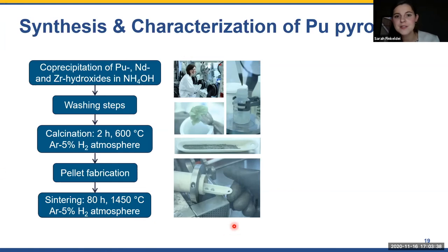And the challenges for the synthesis route were that whenever you work with plutonium in wet chemical form, you have to make sure that you avoid plutonium polymerization, which can happen at certain pH values and if you have too high concentrations of plutonium in your solutions. So what I ended up doing is I wanted to co-precipitate my material. I had a neodymium nitrate, a zirconium oxide chloride, and a plutonium nitrate solution.